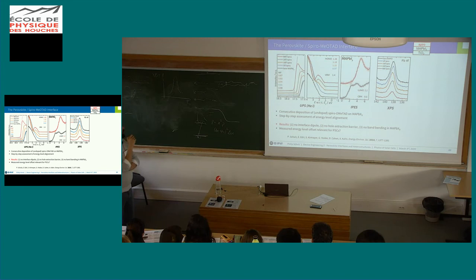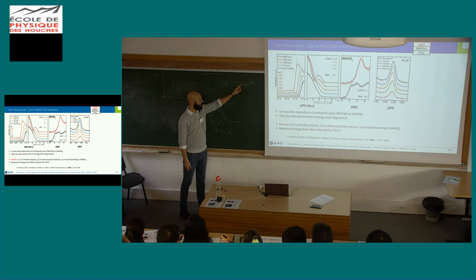We even measured it, so yeah, you're right. You can see a little bit of attenuation here, but you would expect it to be attenuated way more if you're already 8 nanometers thick. The point is that you don't form a conformal layer, right? So this is actually a perfect representation. This is what you actually get, and you're collecting then from thinner parts.